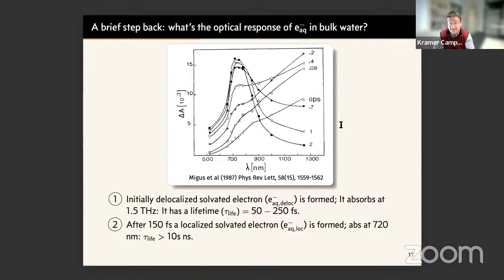So one initially creates a delocalized solvated electron. This is something like a conduction band electron in water. And from the instant of formation, this thing sort of continuously localizes. So in a particle in a box picture, this delocalized electron would have an optical absorption, a Drude-like optical absorption, at DC frequencies. In practice, it's been measured at something like 1 terahertz. If you let it go in time, now it continuously localizes, and after about 150 femtoseconds, 200 femtoseconds or so, one sees now an optical feature that is fairly narrow and centered at about 720 nanometers.